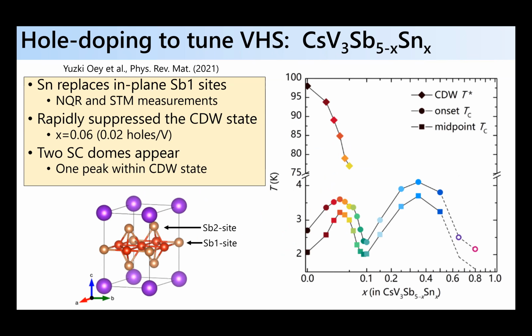Before it disappears, the TC peaks in the charge density wave state and then goes down near the terminus of this CDW state. And then it comes back and you have a second dome out here at higher hole doping. Okay, so that's kind of an unconventional behavior. It's not a simple trade-off between the two states.